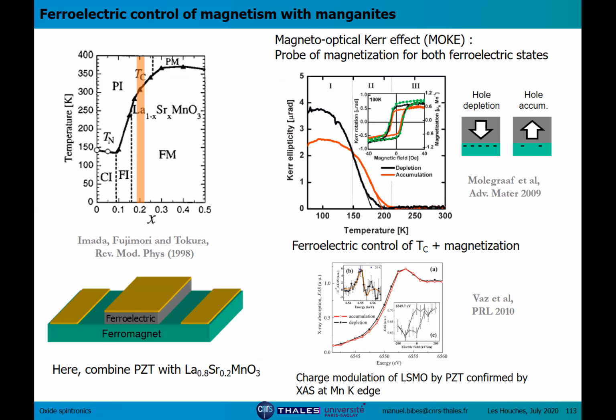So this is by no means exhaustive, but this is work by the group in collaboration with Jean-Marc Triscone, where using some manganites and PZT, I believe, the TC was shifted by maybe 20 Kelvin. And you can also see here that the magnetization depends on the ferroelectric state.